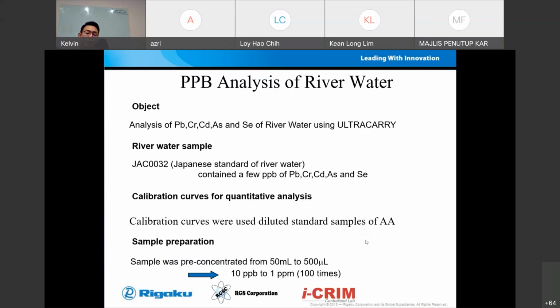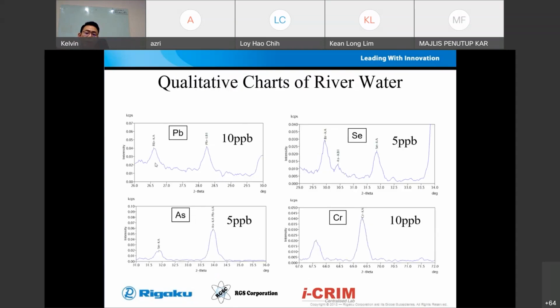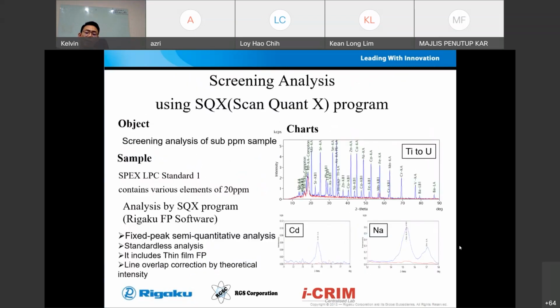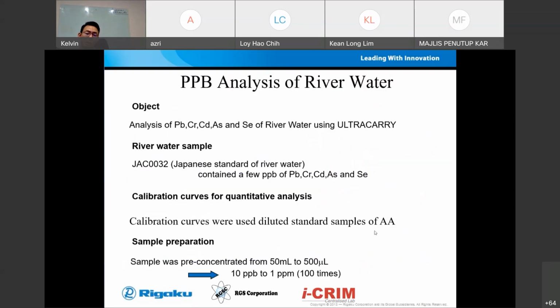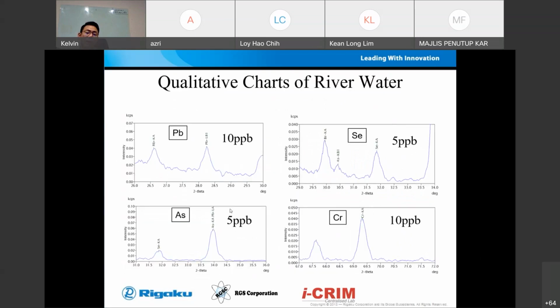So you can actually use your ICP to give you the secondary standard and calibrate the machine. You can see that in the Pb, this is a 10 ppb peak. As long as you can see the peak in the XRF, you can quantify it. If you want a good measurement, you need to get a good peak. Even at this very low concentration, you can get a very sharp peak. That means you have a standard.